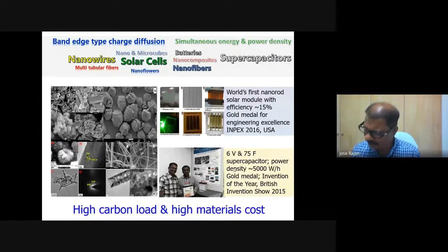Then we started looking at what are our failures in these materials. We find that there are two drawbacks. One is, of course, all these materials have excellent, interesting properties, and some of them were first of their kind in the world. That's why all of that was reported in high-end journals. But to produce them is really expensive, because most of them were metal-based. The second thing is that all these materials were created using a polymeric route. And if we want 1 ton of this material, we probably have to burn about 5 tons of polymer, which adds a huge environmental load of carbon emission.